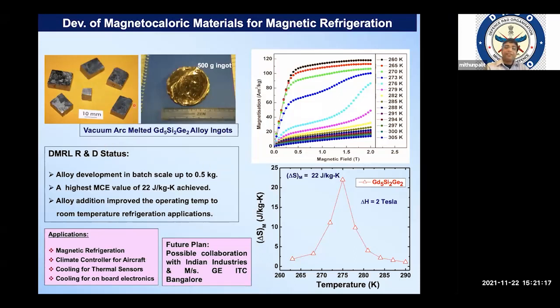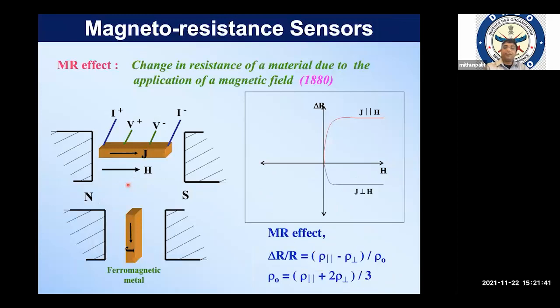In DMRL, we have developed a material, Gd5Si2Ge2, which shows 22 joule per kg Kelvin change in entropy at about 275 Kelvin, and this is quite an excellent property. And we are trying to collaborate with some private industries to make a magnetic refrigeration device out of it.